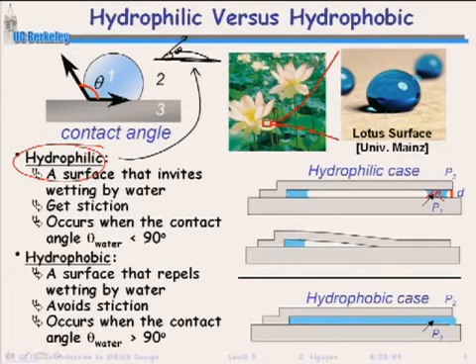Obviously there are many different cases here. It turns out that the hydrophilic case is the case where your device is pancaked down to the surface. The hydrophobic case, where the liquid doesn't like the surfaces, is a case where you will not get stiction. So right away, from this understanding, you can tell that if I want to prevent stiction of devices, I have to make sure that the liquids and surfaces around together with air, assuming everything's operating in air, are such that the surface tensions create a contact angle that's greater than 90 degrees. When the contact angle is greater than 90 degrees, that's your hydrophobic situation. Water doesn't want to coat these different surfaces. Okay, so that's a hand-waving qualitative thing. Let's now take a look at this in more detail here.